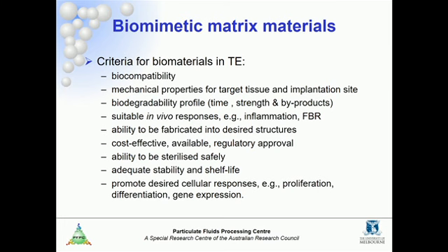So we'd like the materials to biodegrade, and so we're worried then about how long that takes, how rapid it is, and the strength of the material as it degrades. Does it suddenly lose its strength or is it a gradual process? And what byproducts will it release? A number of biomaterials can work very well for a period of time and then they might suddenly release, for example, acidic components. There have been a number of cases where everything seems to be going well and then after 6 weeks or 12 weeks, acid is released due to the degradation of the material and the growing tissue dies. So we need to be careful about that aspect.